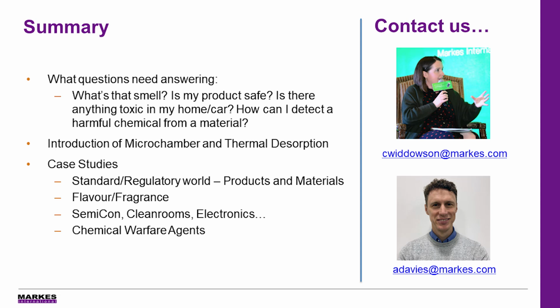Okay, I'll take this one. Actually, the trap can be used from -30 up to room temperature. So what we're talking about here is once we've taken our sample onto our sorbent tube and we place that sorbent tube into our thermal desorption system, we heat our sorbent tube up, and in a flow of carrier gas, we take all of those compounds that we've sampled onto our sorbent tube onto our focusing trap.